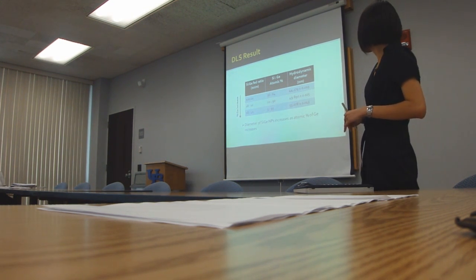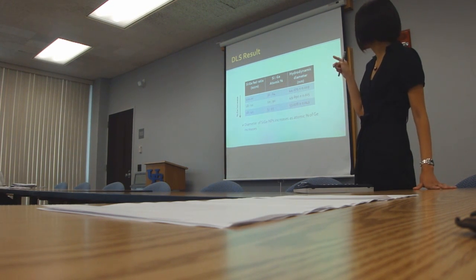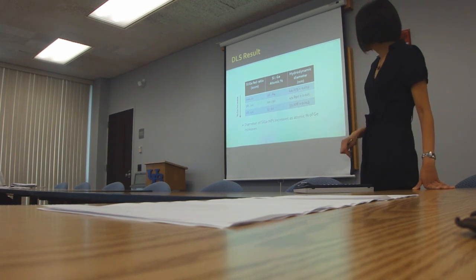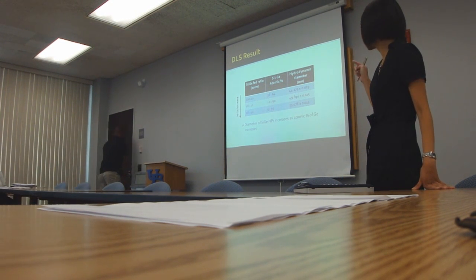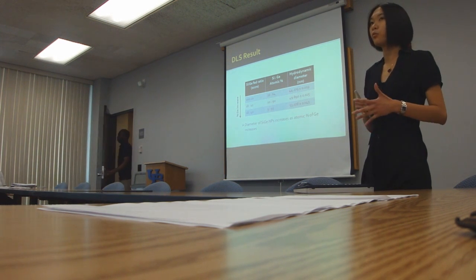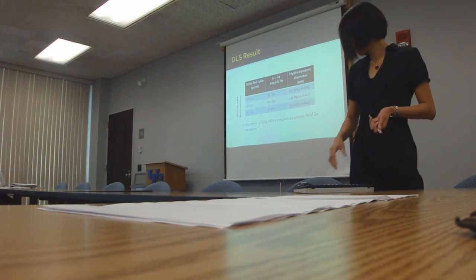For measuring the hydrodynamic diameters, we do the DLS characterization. The diameter increases with increasing germanium atomic fraction, and this trend is consistent with what we found during the TEM experiment.